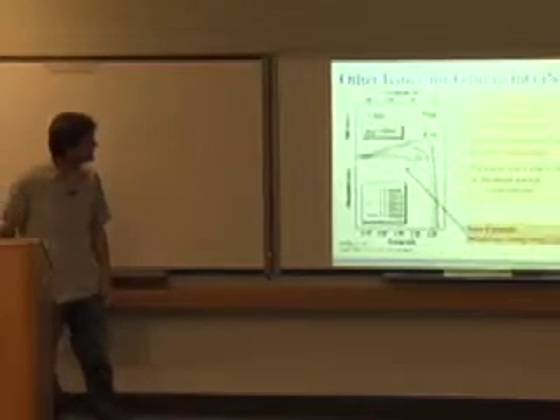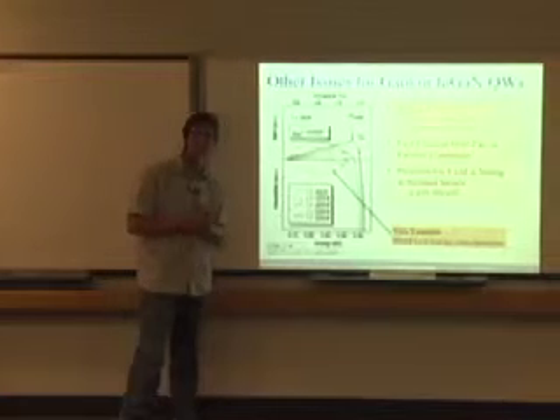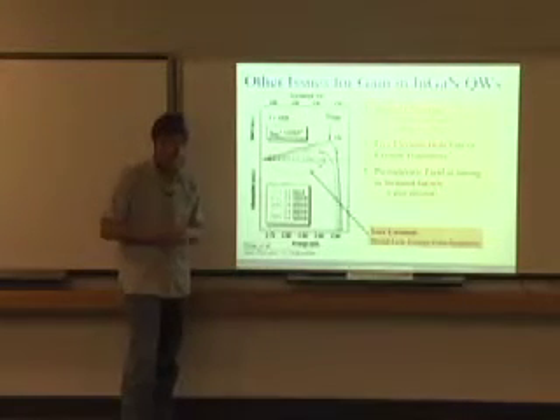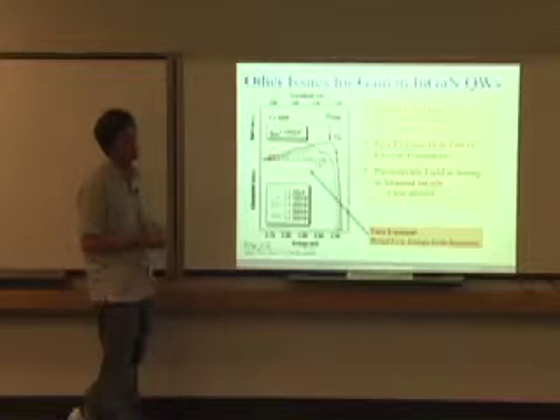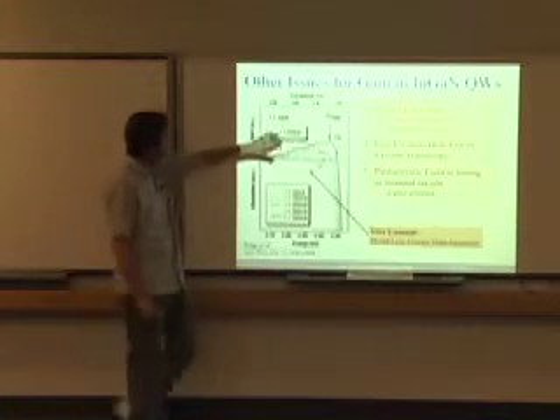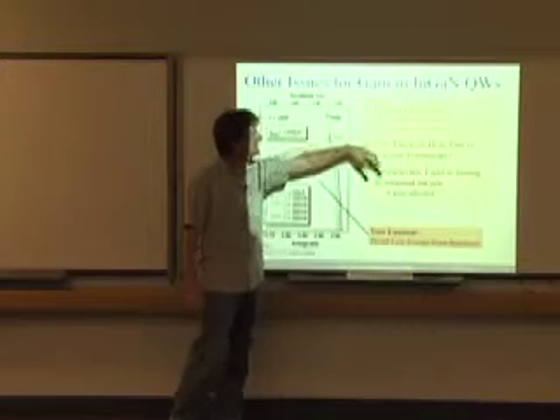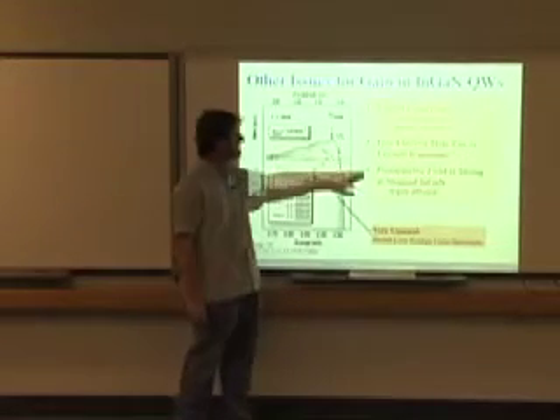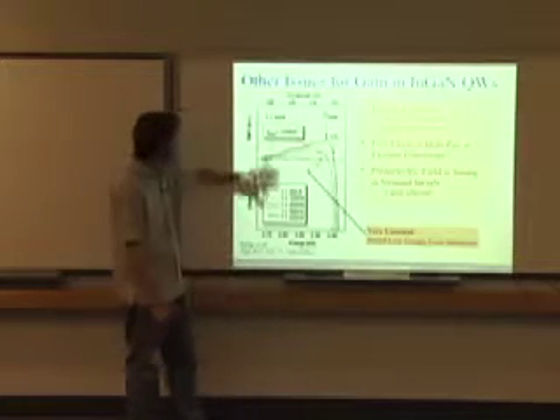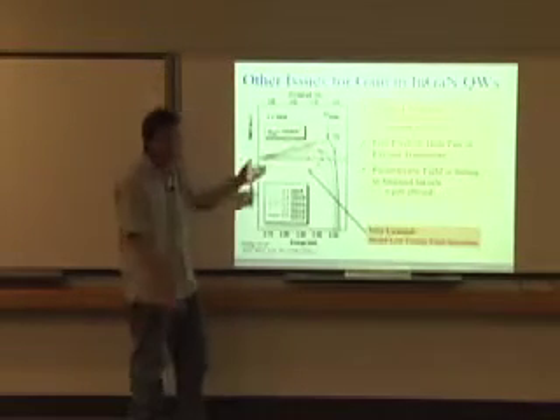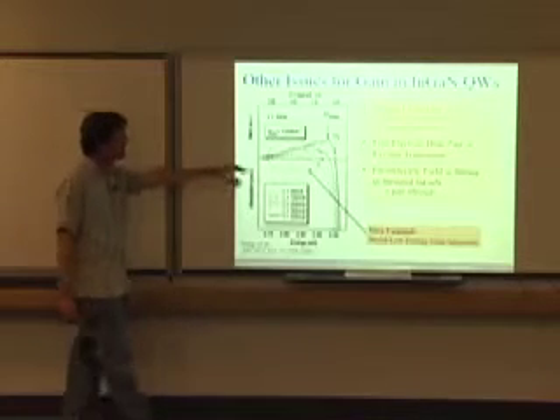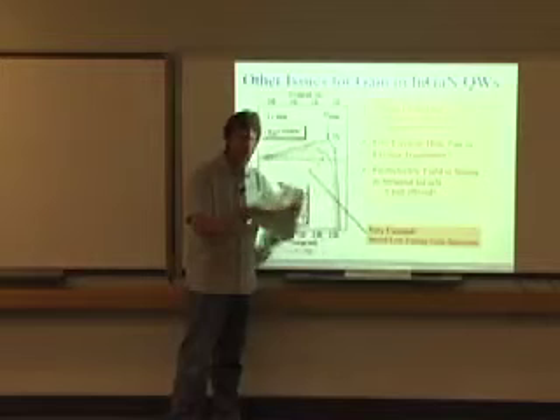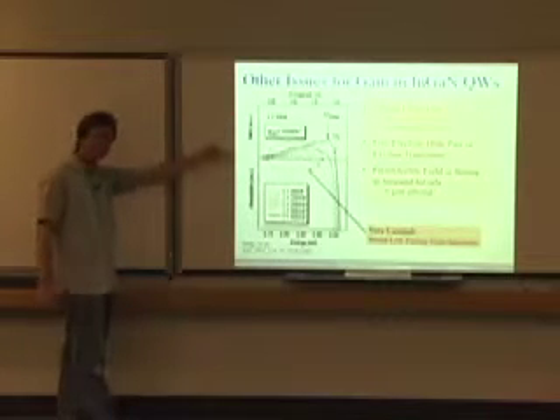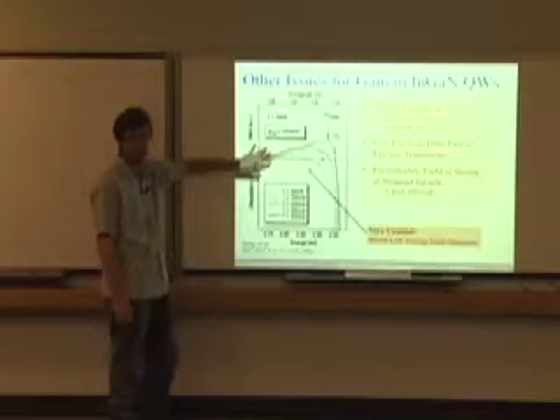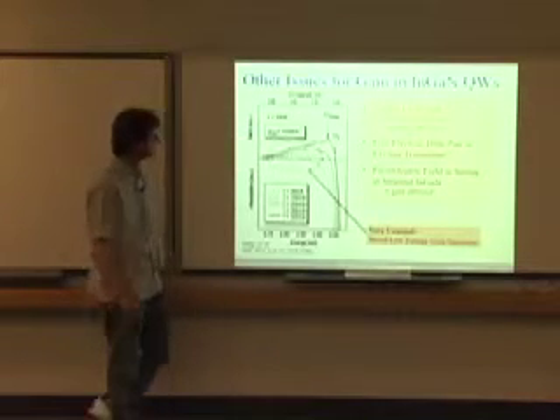However, theory is kind of different from experiment in gallium nitride, because the InGaN quantum wells are not ideal. They don't behave the same as gallium arsenide or InGaAs quantum wells because there are additional components. Indium clustering was suspected. Localized transitions could be occurring, quantum dot effects. Piezoelectric field is strong in strained InGaN layers. And people were observing strange low-energy gain spectra, as well as low-energy emission from LEDs, that was suspected to be due to polarization fields that would exist in the InGaN. So at the time, simple gain theory calculations of this material system were not sufficient to really capture the gain properties of the materials.